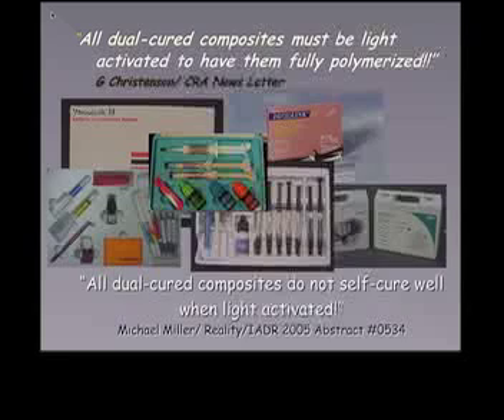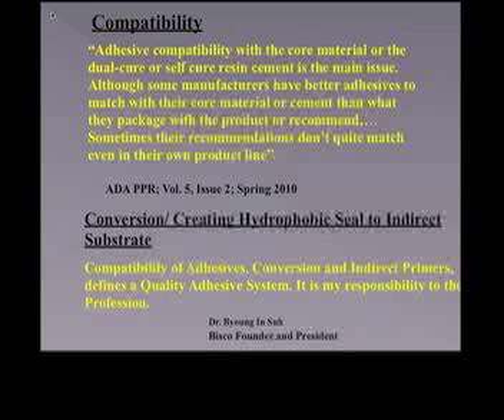The ADA, as I mentioned before, did a study in 2010, spring of 2010, and it just says adhesive compatibility with the core materials or the dual cure or self-cure resin cement is the main issue. Although some manufacturers have better adhesives to match with their core materials or cements than what they package with the product or recommend, sometimes the recommendations don't quite match even their own product line. What is this saying? Compatibility is a huge issue.